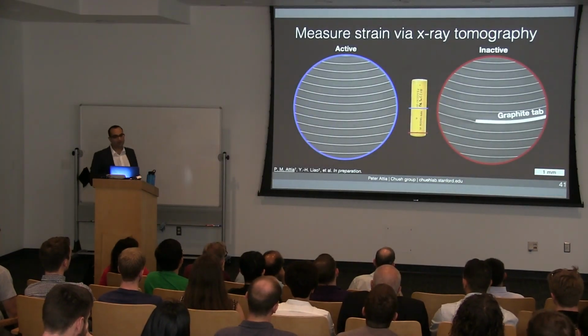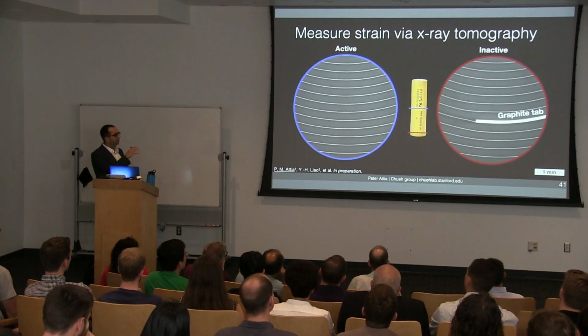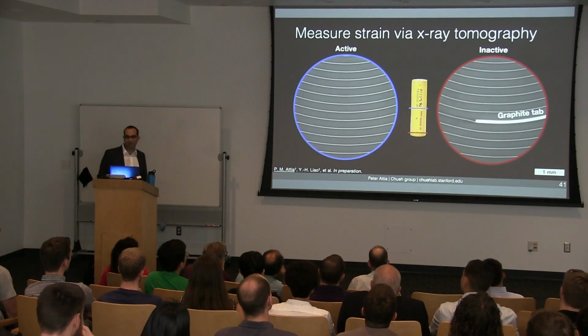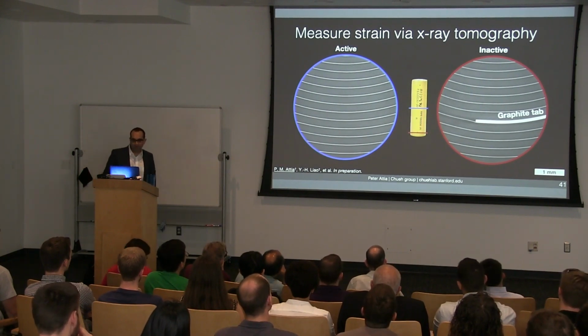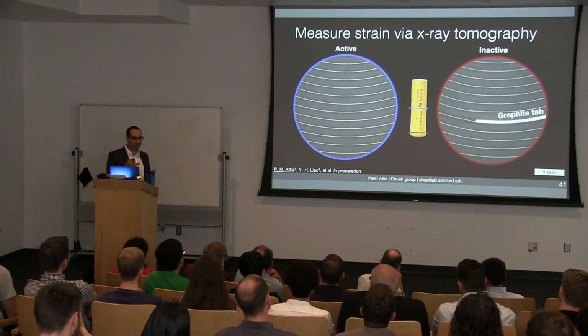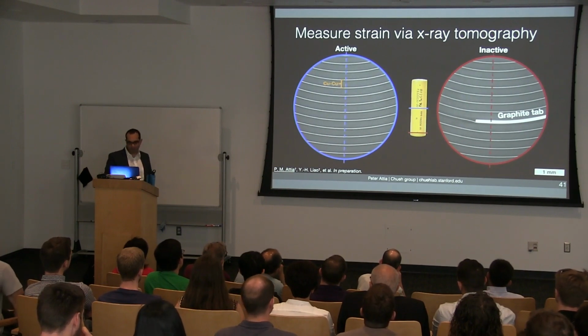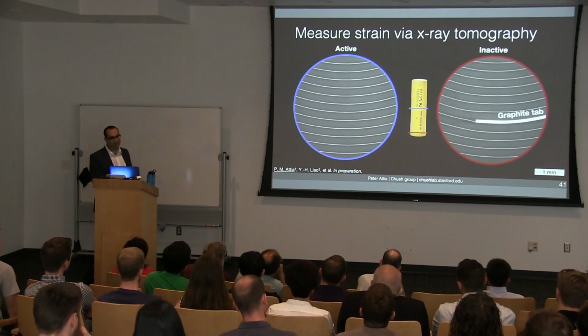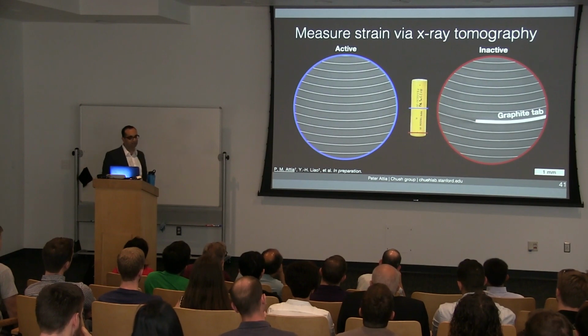We then wanted to quantify what kind of pressure the tabs would have. So we're going to use tomography of a charged cell. Again, tomography is basically a CAT scan. What's really great about this technique is that it's non-destructive, meaning we can look at the jelly roll without taking the cell apart. So here we're comparing active and inactive regions, taken from the center to the bottom of the battery. And the contrast in tomography here comes from atomic number. So the bright lines here are basically the copper current collector of the battery.